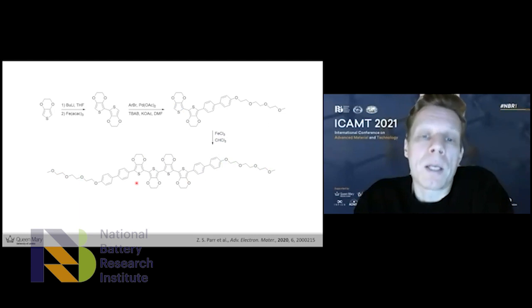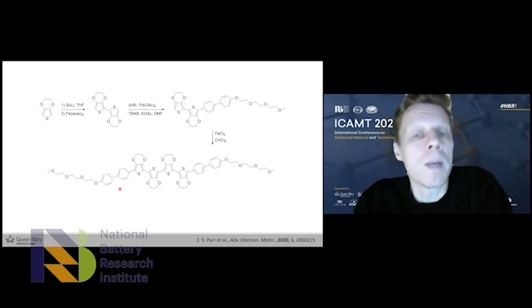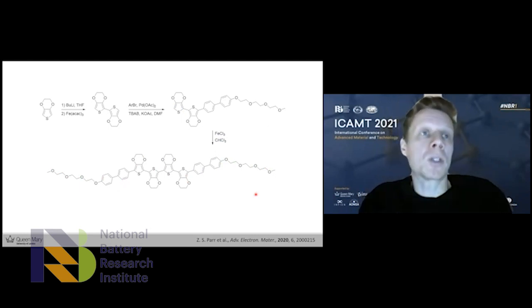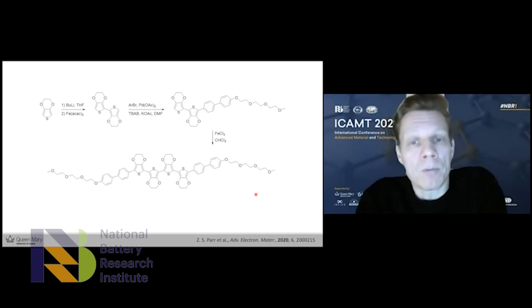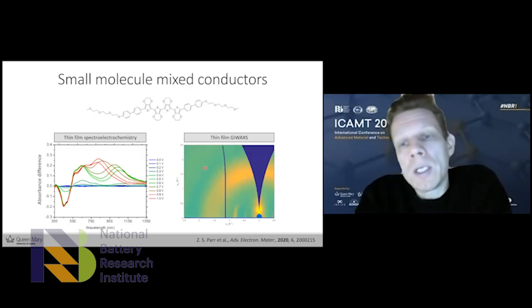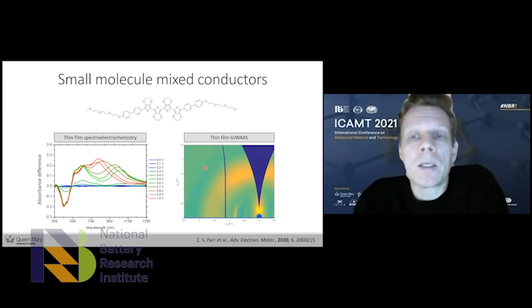So rather than having two EDOTs in the middle, we extended the system to having 4 EDOTs. And also, rather than 1 phenylene unit on either side, we extended to 2 phenylene units. So we made this molecule here, which has a much longer pi conjugated segment, and hopefully better charge transport properties and better film formation properties. And you can see here in the GIWAXS, in the X-ray, it's much more polymer-like. It's not as crystalline as the other small molecules, so that's a good thing.